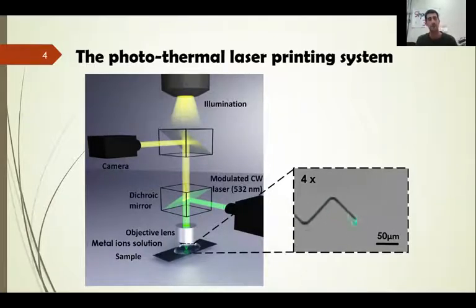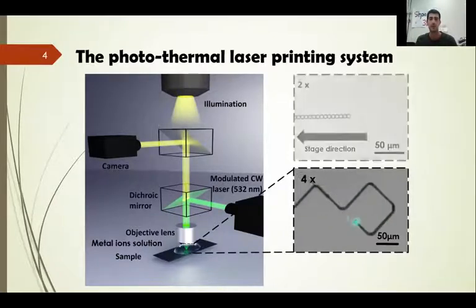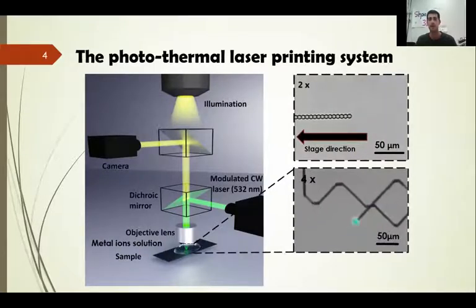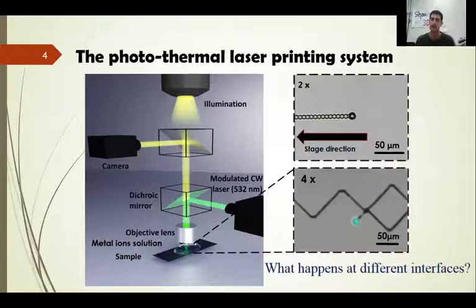pattern or structure. So the first step in our research is to understand the deposition mechanism in our technique. We saw that we have a microbubble involved in our process, and the deposition occurs at the interface between the gas, liquid, and solid from the microbubble, metal ion solution and the substrate. So we thought that the best way to understand the deposition mechanism is to know what happened at the different interfaces. So we suggest separating our process into 3 different cases that depend on the different interface.